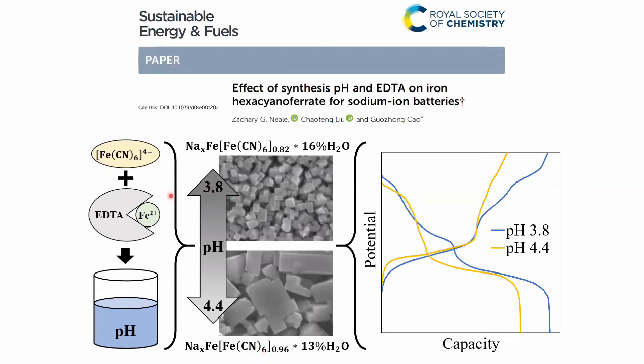So you see the material that was synthesized at a lower pH had more vacancies than the material that was synthesized at a higher pH. And the reasoning behind that is that at higher pH, the chelation strength of the EDTA is greater, which slows down the reaction. And if you have a slower reaction or slower nucleation, you allow more time for crystal growth. And if you have slower crystal growth, then it becomes a more perfect crystal with fewer vacancies.